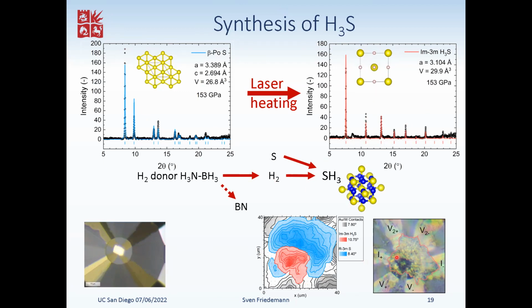The black stuff on top is most likely either boron nitride or one of those polymers. This one peak there, the largest peak that is not fitted by our X-ray diffraction, is in fact consistent with boron nitride. So it suggests that we indeed have boron nitride present on top of the sample, the hydrogen probably then having diffused into the sample and reacted with the material.